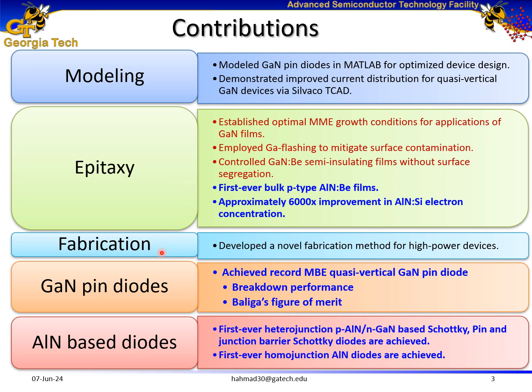From the fabrication point of view, I have developed a novel fabrication method for high-power devices. I have achieved a record MBE quasi-vertical gallium nitride pin diode in terms of breakdown performance and in terms of Baliga's figure of merit. I have shown the first ever heterojunction P-type aluminum nitride on N-type gallium nitride based Schottky, pin, and junction barrier Schottky diodes. And finally, I have achieved the first ever homojunction aluminum nitride diodes.